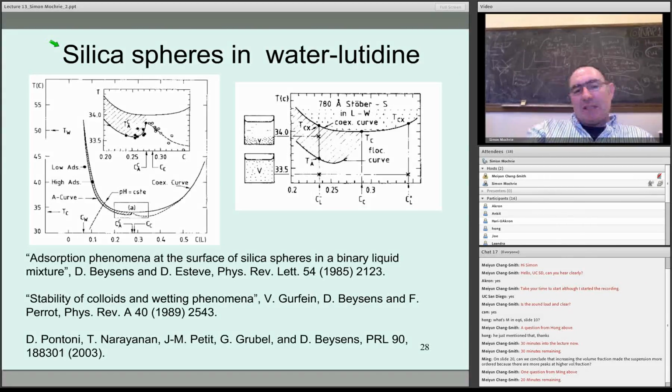We picked this particular system because it's been known since the 1980s that if you adjust the temperature to be close to the consolute point, the point at which these two liquids, water and lutidine, unmix, at a temperature below that phase separation, so these two materials have an inverted coexistence curve, so this is up here, at high temperatures they're phase separated, at low temperatures they're mixed.